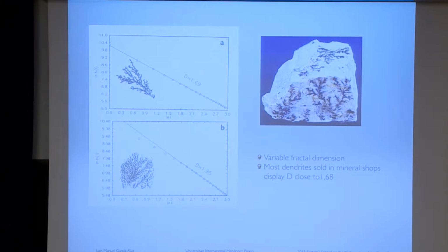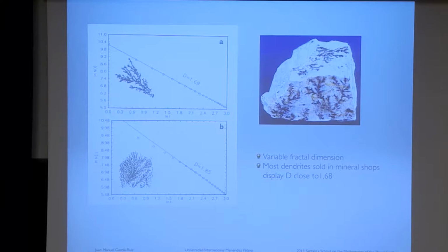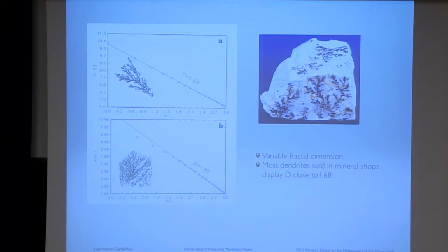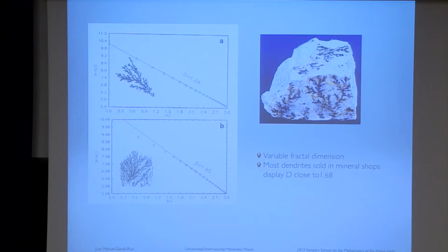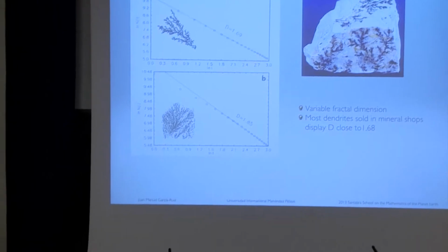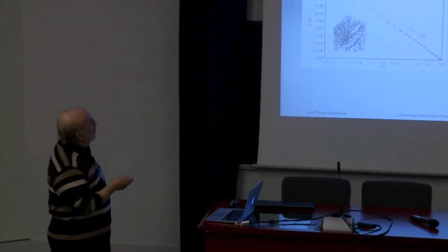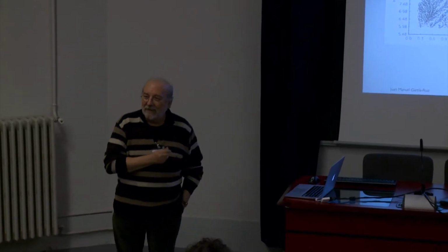We went to different places to find these dendrites, but also we went to the mineral shops. Then we measured the fractal dimension of different kinds of dendrite, and it was very interesting that for the dendrites that we found in the countryside, there are many different fractal dimensions, but the ones in the mineral shop all go about 1.68. Okay, so maybe this is, let's say, a golden number for fractal geometry, right?